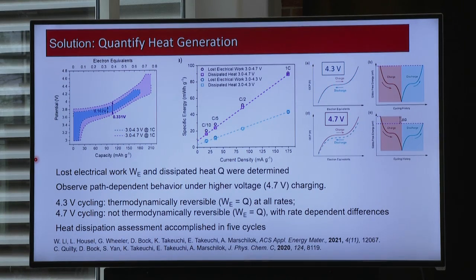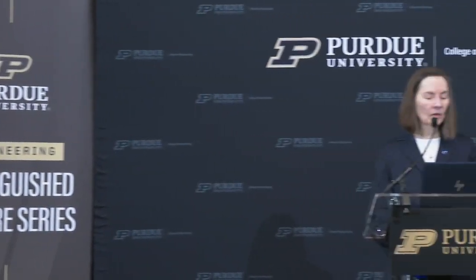When we looked at the heat and work contributions, we find out that from a thermodynamic perspective, when we charge to 4.3, the system is largely reversible. But when we charge to 4.7, the system is no longer fundamentally reversible. And we plotted to see how much that offset is.